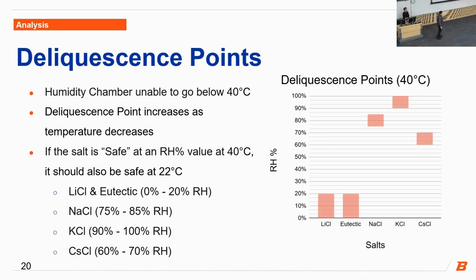With this in mind, we did deliquescence testing, and we found that the deliquescence point is somewhere between 0 and 20% for lithium chloride and eutectic. It is between 75 and 85% for sodium chloride, somewhere above 90% for potassium chloride, and between 60 and 70% for cesium chloride.